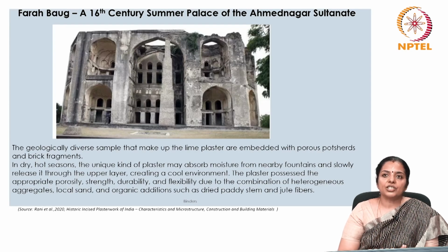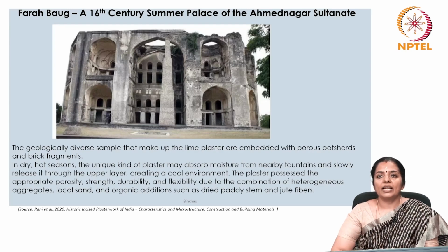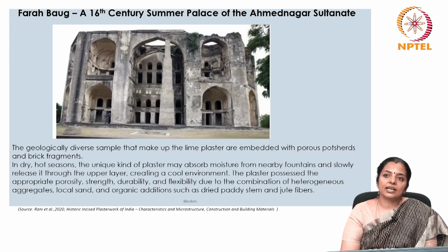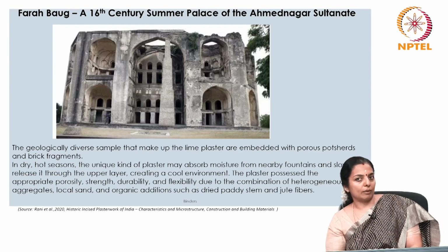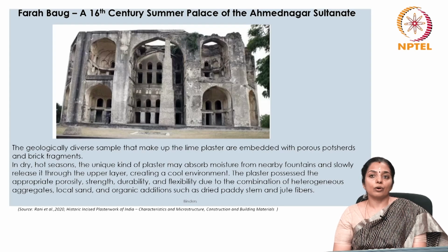The National Museum Institute of the History of Art, Conservation and Museology and the ASI, Chennai, analyzed the material used in the palace's construction, and they found that its 13 centimeter thick lime plaster was embedded with stone, fired pottery and brick pieces that improved its permeability. Sand, jute fiber and dry paddy stem increased its porosity, durability and flexibility, helping the plaster to absorb moisture from the surrounding water fountains.